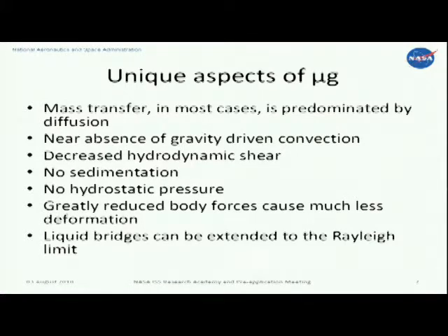And the important thing in solidification is the solidification velocity vis-a-vis the flow velocity. So for example, if you grow crystals, protein crystals or whatever, if the growth velocity is 1 millimeter a day, then flow velocities of that order will have a significant effect. May I have the next slide?